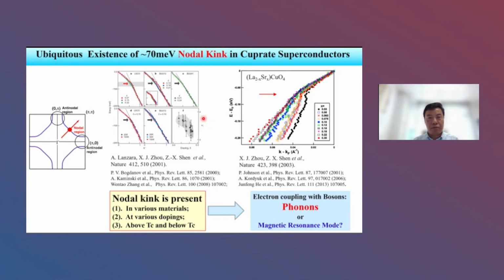So it has been found that in many hole-doped superconductors and also electron-doped superconductors, there's the nodal kink. In the nodal region, there's a 70 millivolt kink present in different materials like Bi2212, 2201, laser ARPES studies, and many others, and in various dopings, and also above Tc and below Tc. But it's still controversial whether this mode is due to phonons or some other modes, some magnetic mode. It's still under debate. But people already see that there's a 70 millivolt nodal kink in cuprate superconductors.